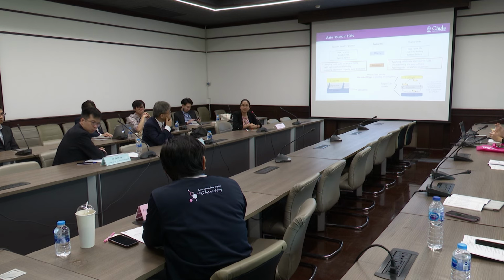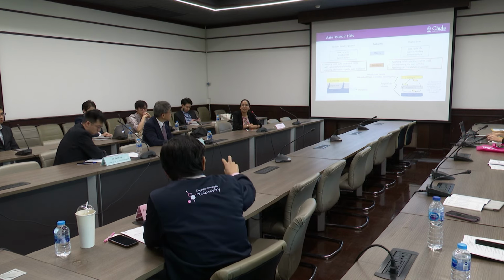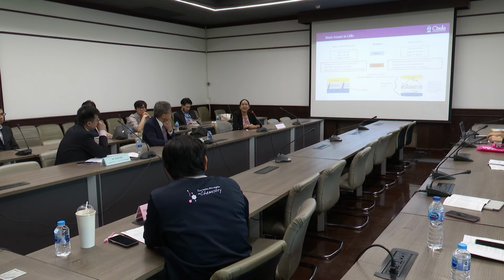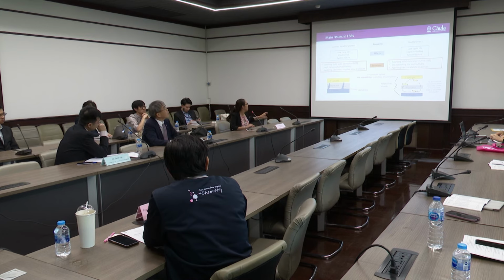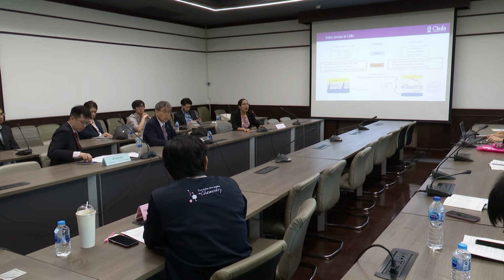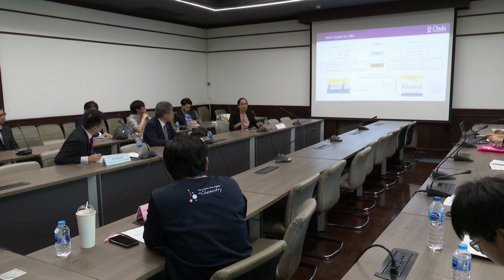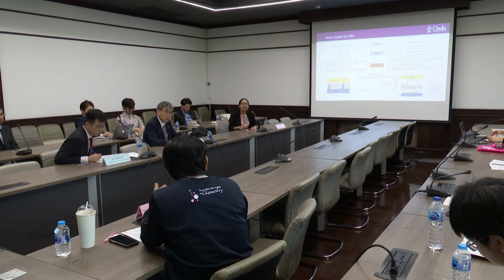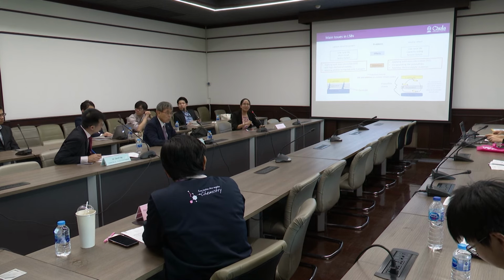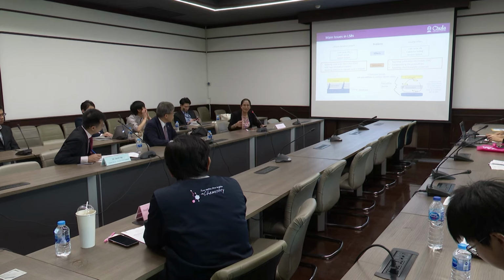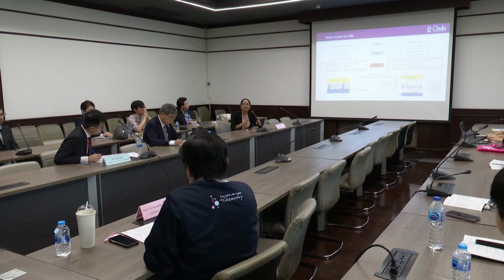According to the previous question, did you try to characterize that the additive you add really prevents dendrite growth? The additive is added to enhance the electrochemical properties, but not about dendrite growth. So what prevents the dendrite growing? We try to prevent the dendrite; the electrolyte is the main part, but the mechanical strength is also important. But did you characterize the dendrite growing? No, so far we have not characterized the dendrite. We just characterize the performance of the battery based on cycling and conductivity, very simple ones. Maybe in the future.